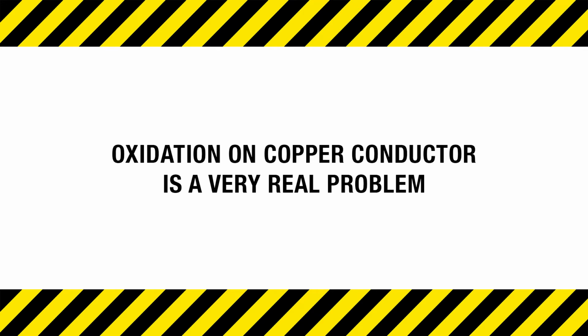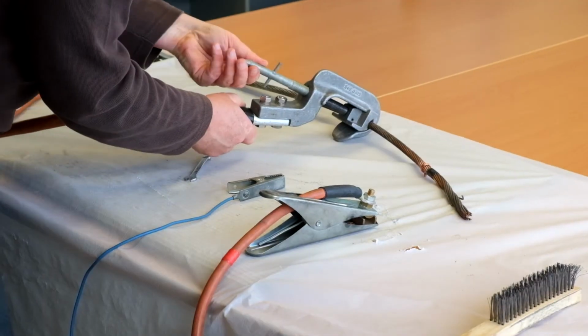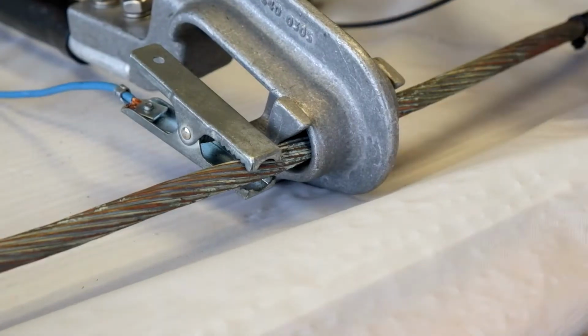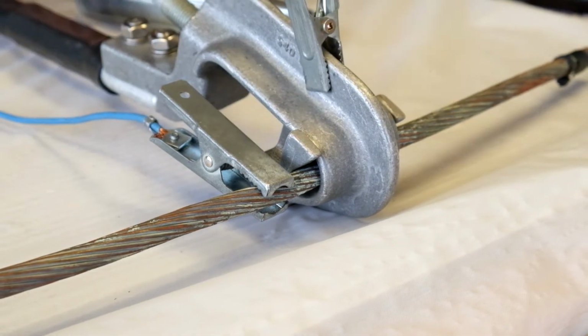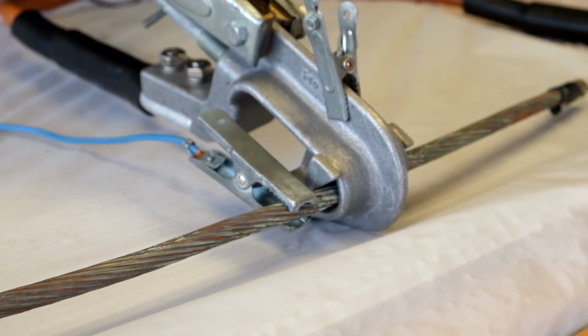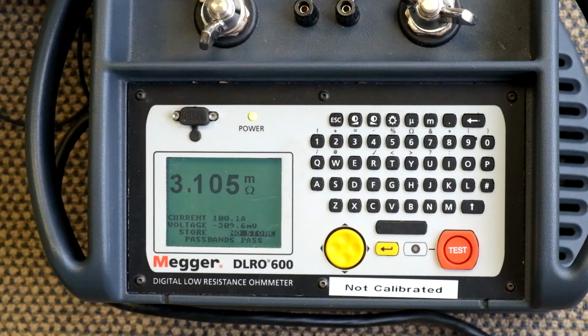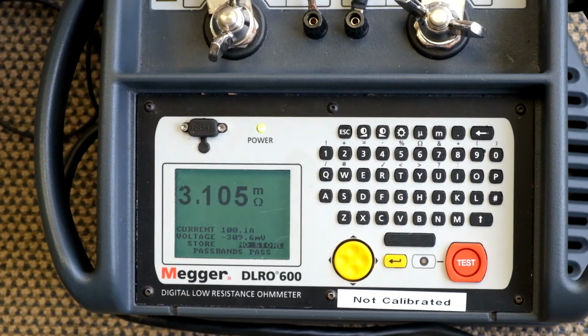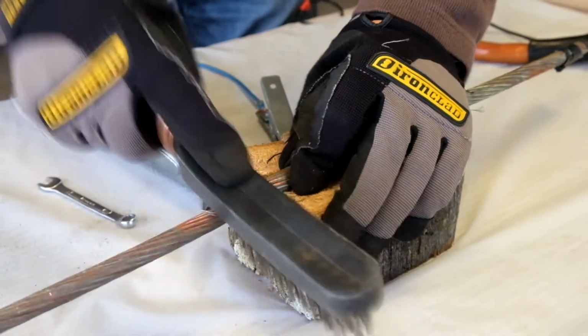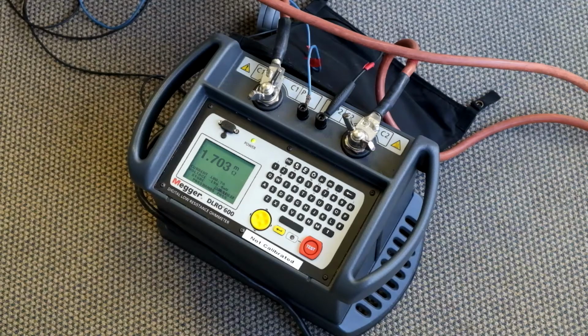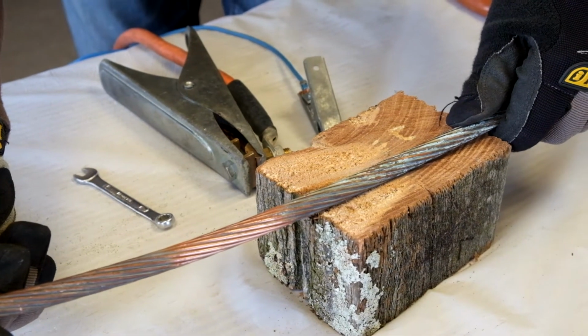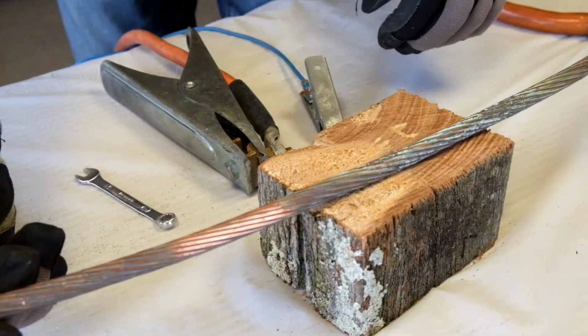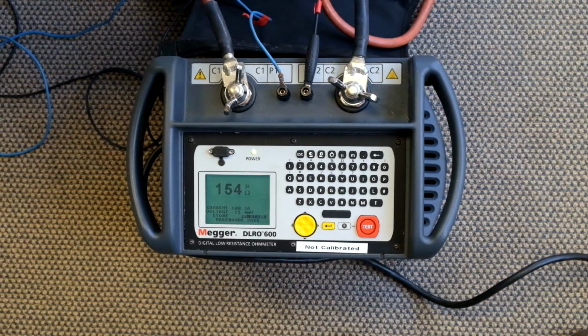Oxidation on copper conductor is a very real problem when trying to apply temporary earths. Conductor 3. In the next example, we are testing a piece of copper conductor that has a layer of visible contamination on the surface. Before any cleaning takes place, the ohm meter returns a result of 3,105 milliohms. After an initial clean, the result is still far too high, at 1,703 milliohms. After an extensive clean, taking several minutes, we managed to get the result down to 154 milliohms.